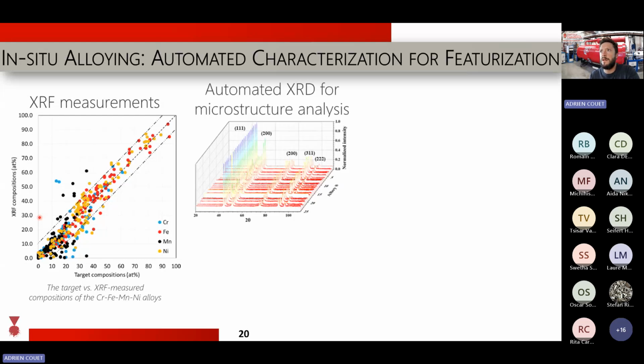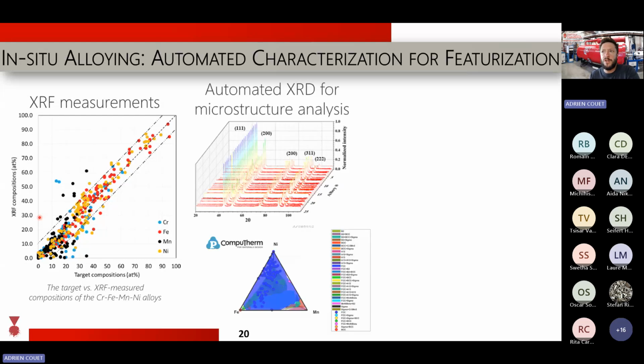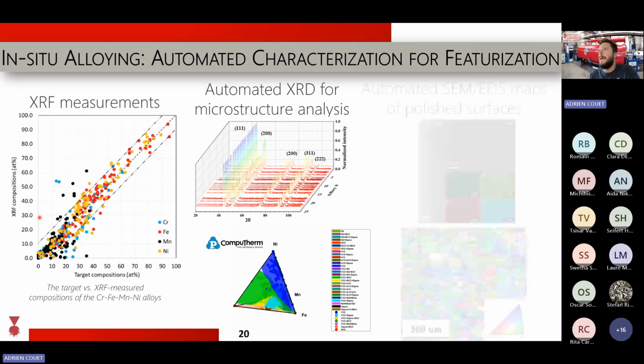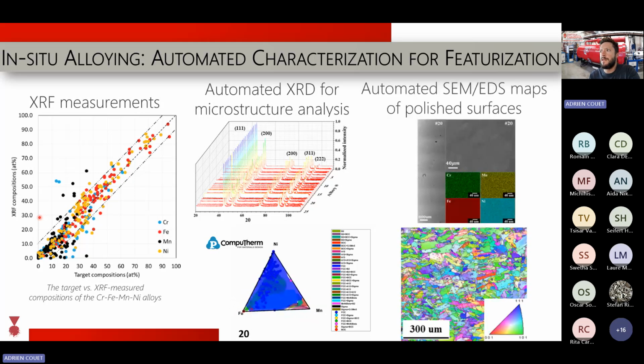We can use automated XRD to check the crystal structure. As I mentioned before, then we check relative to the predicted CALPHAD-based databases. And then we can also do SEM and EBSD to look at the crystal structure and the SEM-EDS. One of the issues we have here with the crystal structure is you can see it's not really recrystallized. And that's one of the things we have to do a better job on, the heat treatment of our additively manufactured parts, especially when we go to refractories.